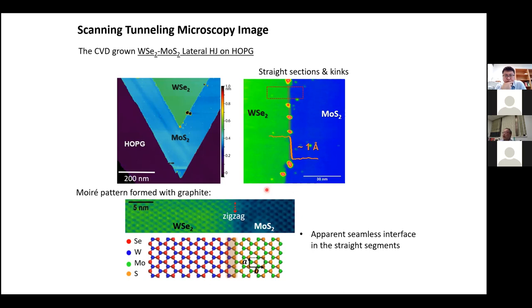But we can calibrate it, okay? In the direct image you may not see that very clearly, but if you calibrate it, we see that from here to here for the MoS2, the lattice constant doesn't seem to get stretched. Here it would be 4%, right? Therefore there must be strain at the interface, and going further, we'd like to know the behavior of that strain. The formation of the moiré pattern does provide some amplification factor. So if you have a lattice mismatch of about 4%, then your moiré pattern will be about 25 times your real lattice.